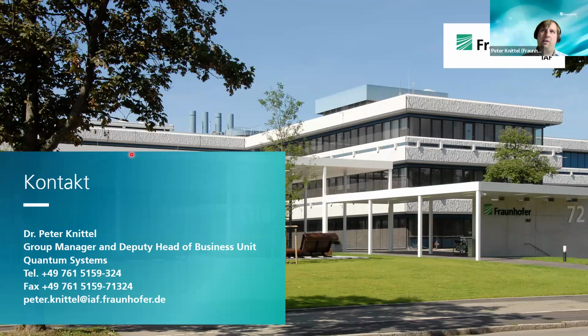So yeah, this is basically a bit of a work in progress. I've shown these delta doped layers, and these layers ultimately, at least that's what I think, may replace the implantation pathway, because it should end up with better quality, meaning higher coherence times, higher stability, and better controllability. But this very thin growth of especially individual color centers is quite delicate. It's difficult to achieve and requires also very long characterization times. So the feedback circle is rather time consuming, and that's why at the moment I cannot really say definitely that it works well, because it may also have some drawbacks that we don't foresee at the moment. But in principle, it should be able to replace it ultimately at some point.